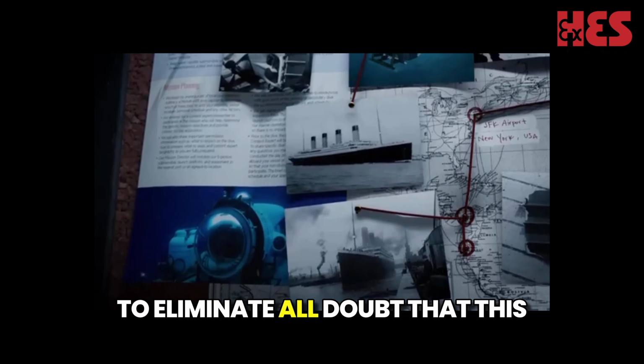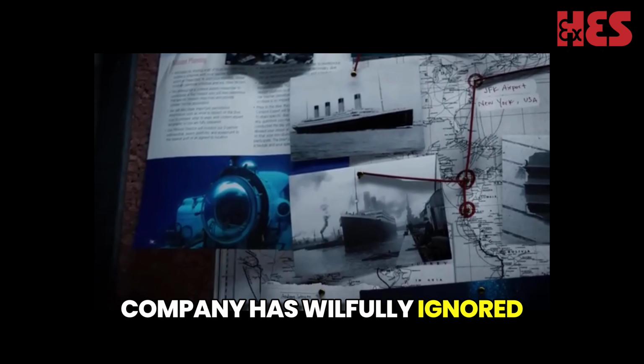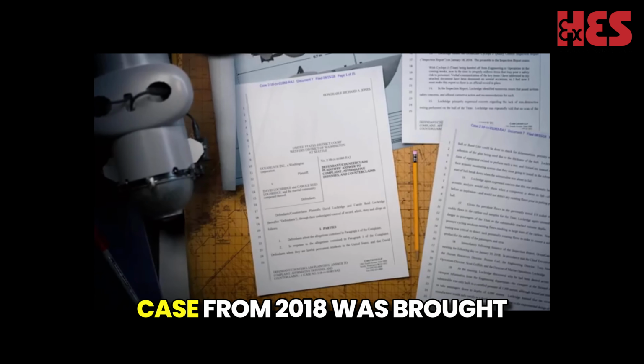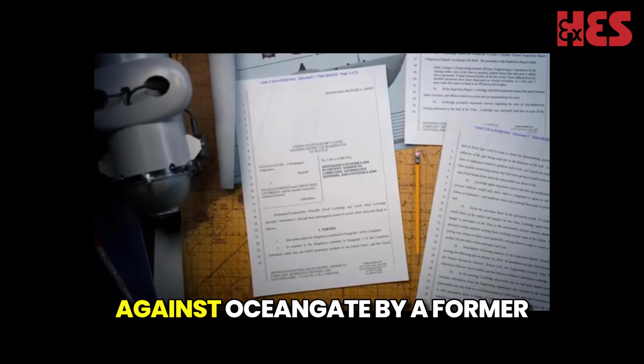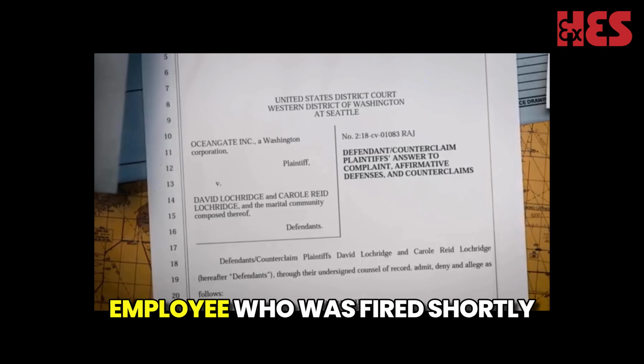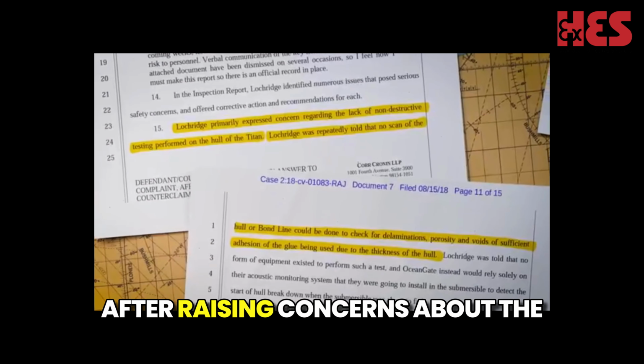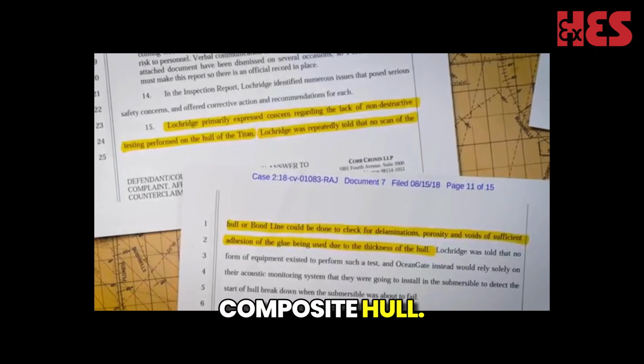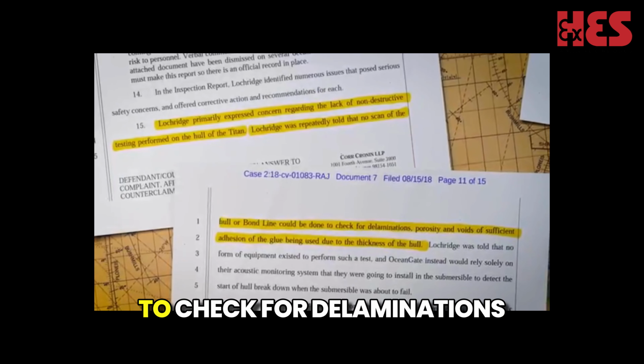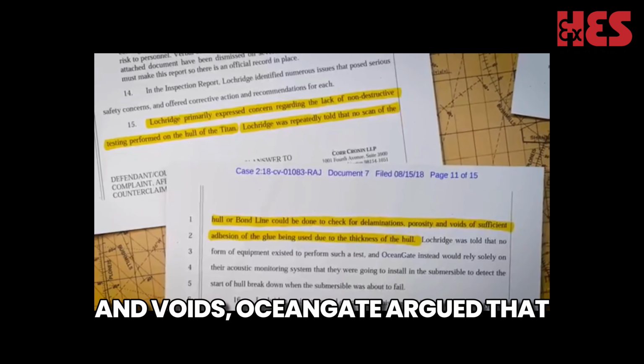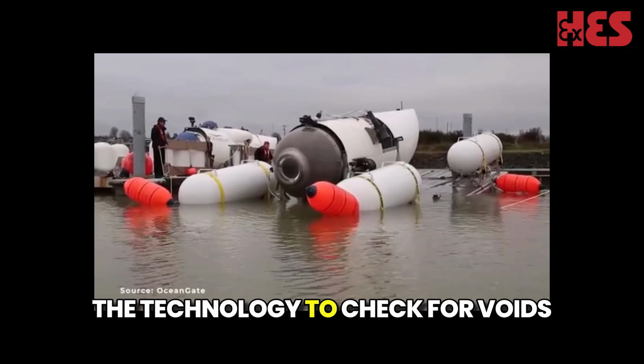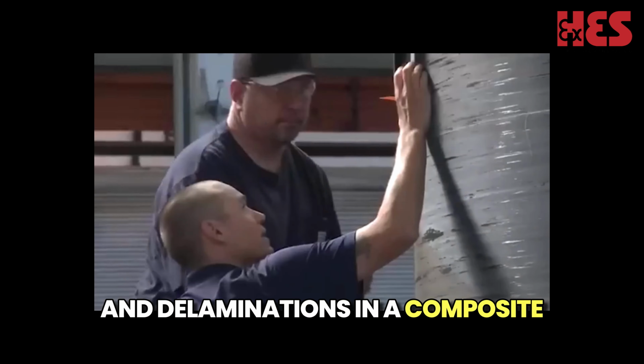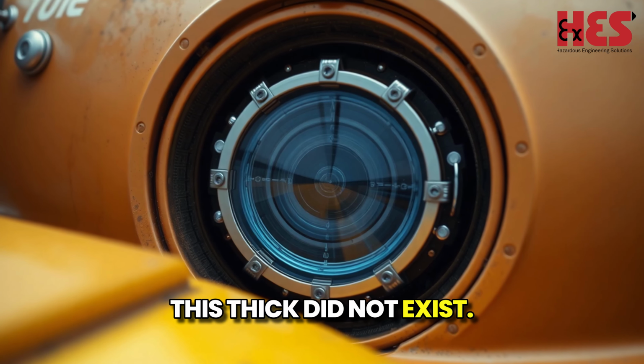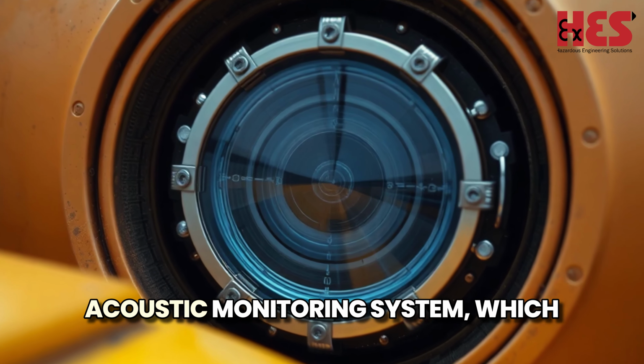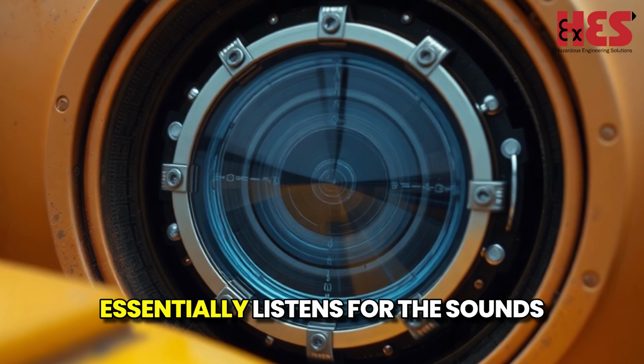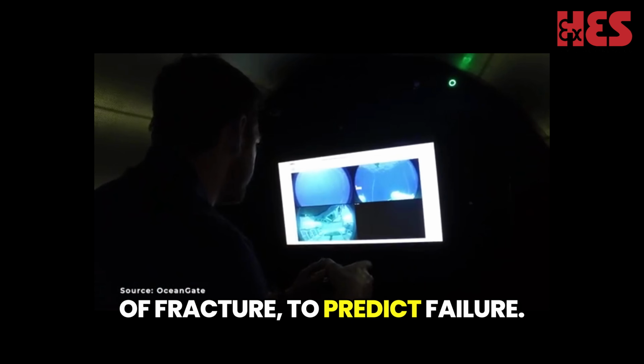To eliminate all doubt that this company has willfully ignored safety standards, this court case from 2018 was brought against OceanGate by a former employee who was fired shortly after raising concerns about the composite hull, stating that not enough was done to check for delaminations and voids. OceanGate argued that the technology to check for voids and delaminations in a composite this thick did not exist, and instead they would use their acoustic monitoring system, which essentially listens for the sounds of fracture to predict failure.